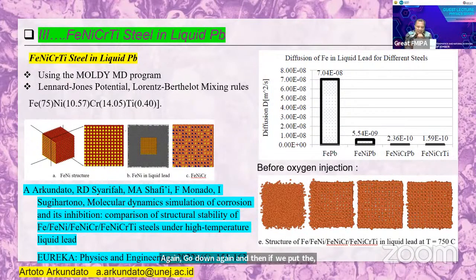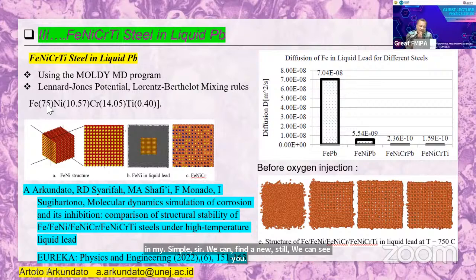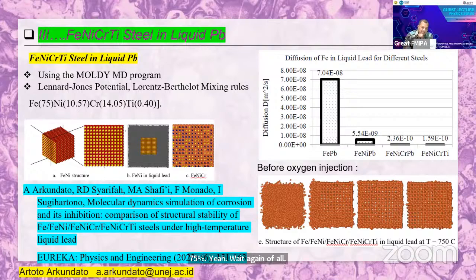So in my research, we can find a new steel. We can see here iron has 75% weight of all. So weight percent. Nickel around 10, chromium around 14, and titanium very small, around 0.5. This is, let's say, maybe a promising field for use in LFR design.